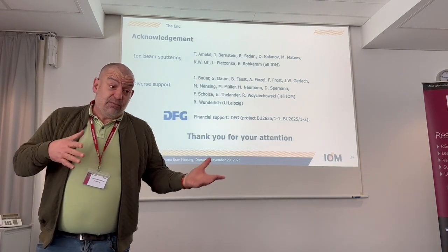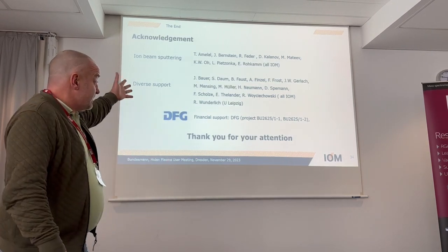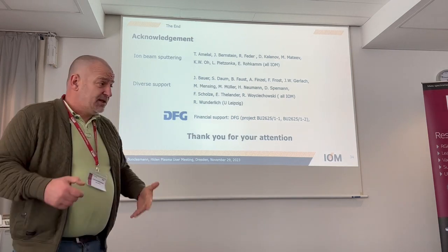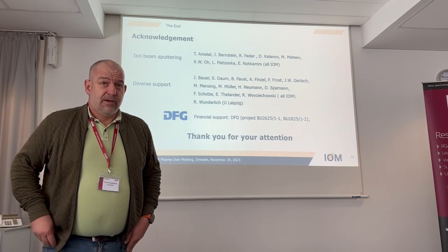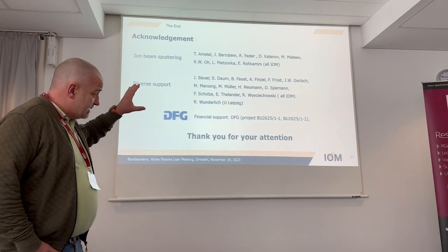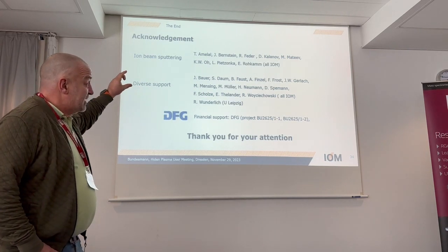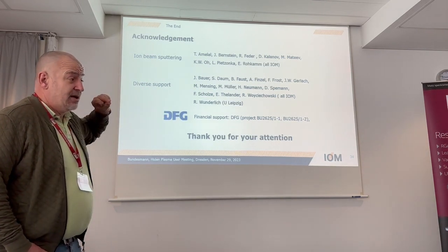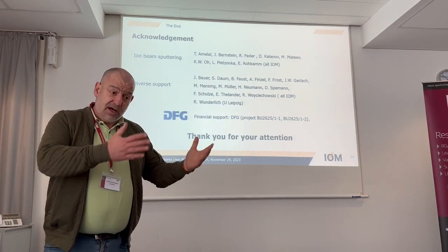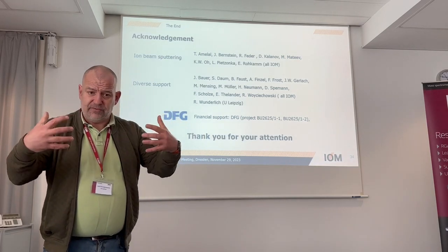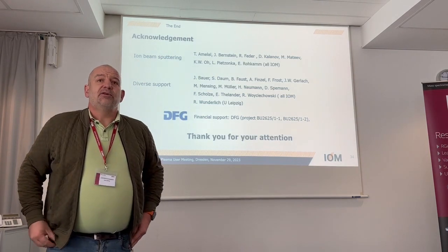So that's why this number is probably related to some high energy argon ions, but we saw that the low energy peak was several orders of magnitude higher. But still we see that this small number, even though it's several orders of magnitude smaller than the low energy part, plays an important role. By just comparing the data for silver with argon and xenon, you see there is a difference, and the only difference in the particle properties are these high energy scattered primary particles.